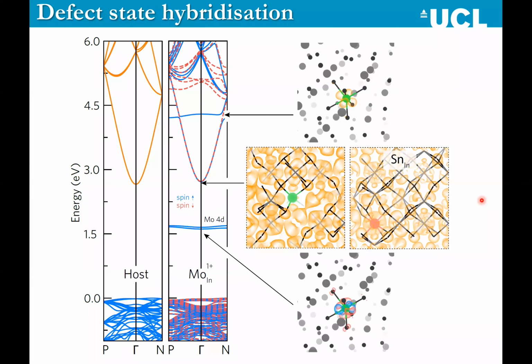So to look at the effect of these donor dopants on the system, we can look at the orbitals that make up these bands. So obviously these 2 molybdenum D states in the middle of the band gap, they're completely centered on the D orbitals of molybdenum. When we look at the bottom of the conduction band, the molybdenum dopant has no character whatsoever at the bottom of the conduction band. It's all indium and oxygen states mixing.